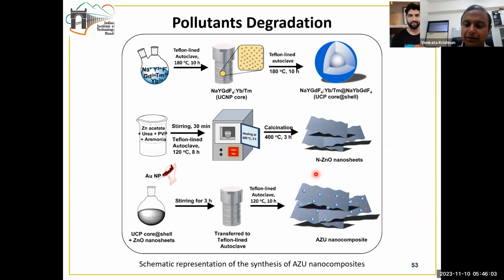On the other hand, we have taken a nitrogen doped zinc oxide, a semiconducting material, wherein we have matched the band gap of the semiconductor to fall within the region of the light emitted from the upconversion nanoparticle. So the light emitted from the upconversion nanoparticle gets absorbed onto this semiconductor. When it's absorbed by the semiconductor, that leads to the promotion of an electron from the valence band to the conduction band. And in order to enhance this photocatalytic effect, we have also decorated this material using gold nanoparticles, which have the surface plasmon resonance effect, which can further enhance the visible light absorption capability.